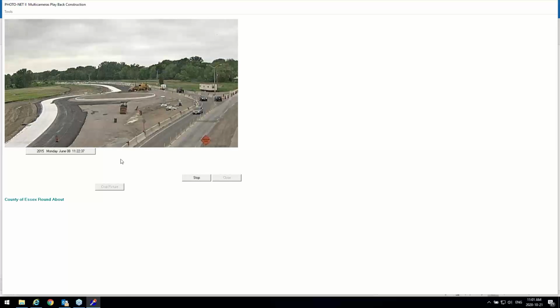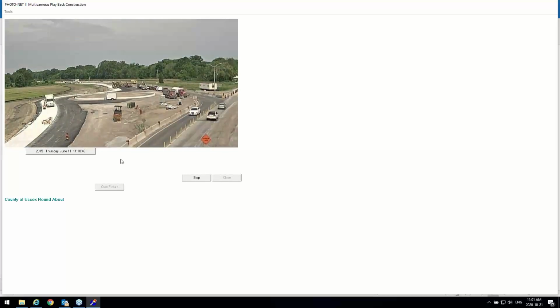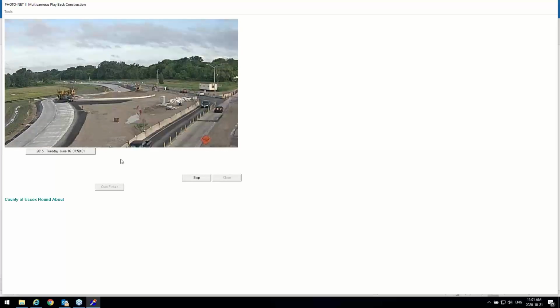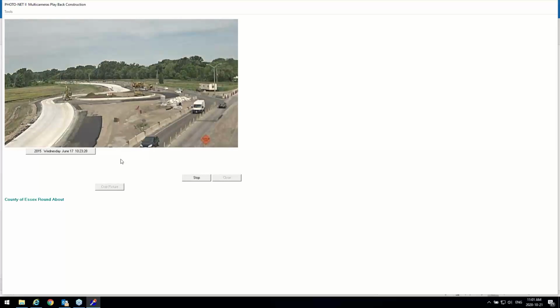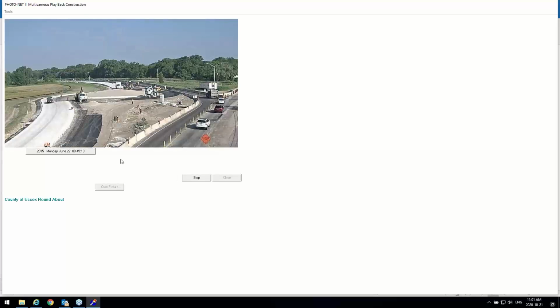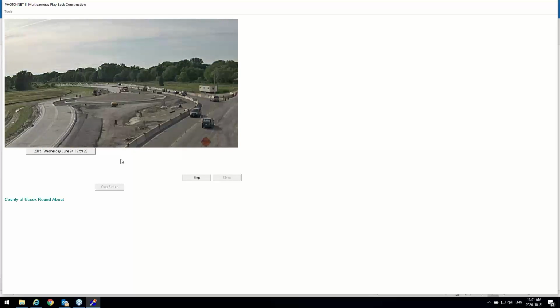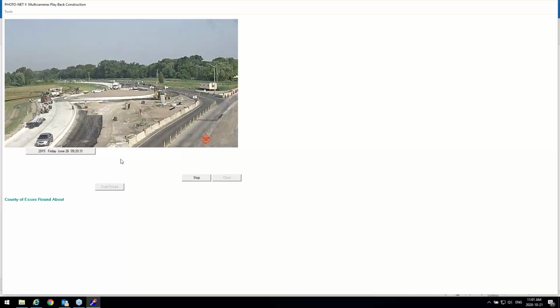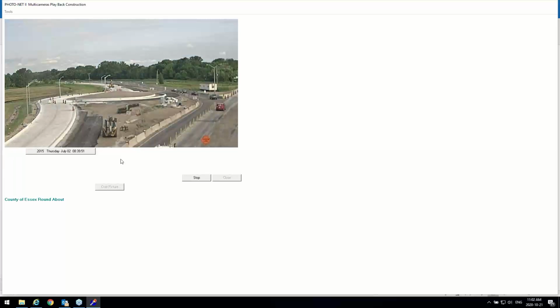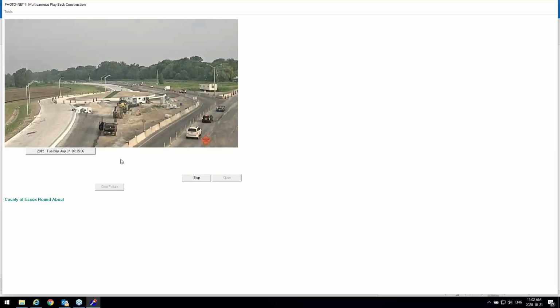So as we just let it roll, you start to see more construction. And Peter, you should note that's on an open graded drainage layer. Oh yes, sorry, that's true. So part of the design of this roundabout is the concrete is on an open graded drainage layer, which basically consists of clear stone with an asphalt cement coating. So that's why you see the black layers going down ahead of the concrete. That's not asphalt per se. It's the drainage layer, which has the asphalt cement on it.